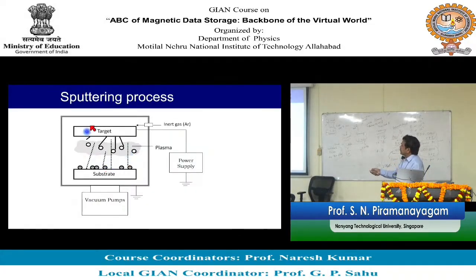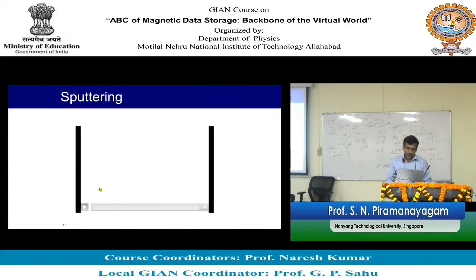Okay, so this is a simple view of a sputtering chamber. You have a chamber, and inside you have some target, and here you have the substrate, and this chamber you pump using a vacuum pump. Sputtering is typically carried out at 10 to the power minus 7 torr or even lower pressure. So we evacuate the chamber to a low pressure. Then we send inert gas into the chamber, and we apply a large negative voltage to the target. During this process, the target attracts argon ions, they knock the target atoms, and the atoms get deposited onto the substrate. Okay, I'll play another video to describe the whole process.